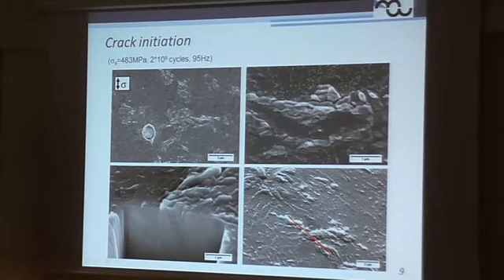Now I want to show you two examples for runout specimens. The first example is a specimen which has been loaded up to 2 times 10 to the power of 8 cycles with a testing frequency of 95 Hz. The first thing we can obviously see is that this aluminium-based inclusion does not affect the fatigue life in any way, but in the surrounding area we can observe again this surface roughness. And if we have a closer look, it almost looks like a small crack which is already open against the surface.